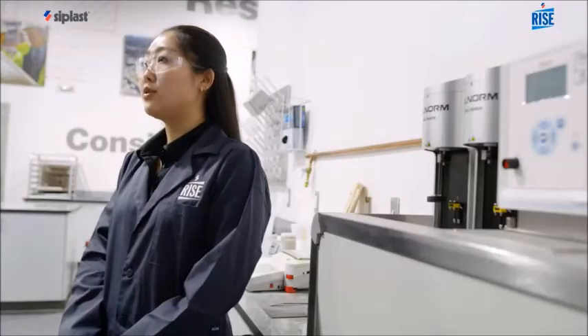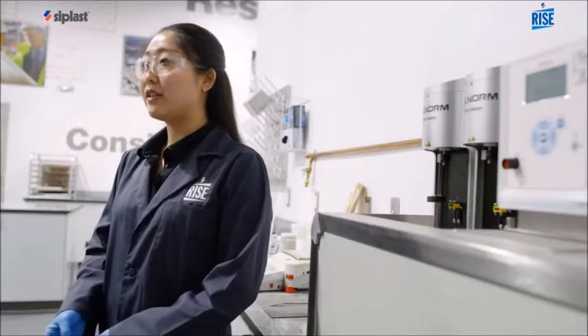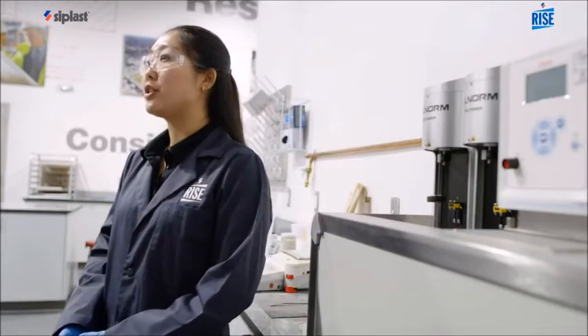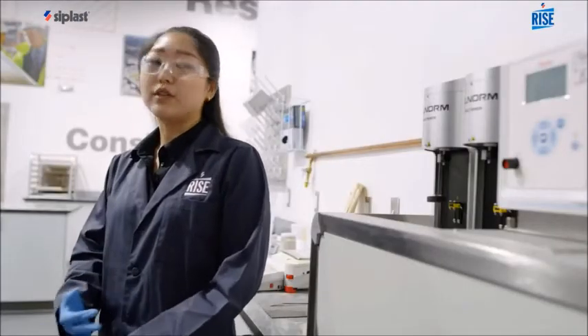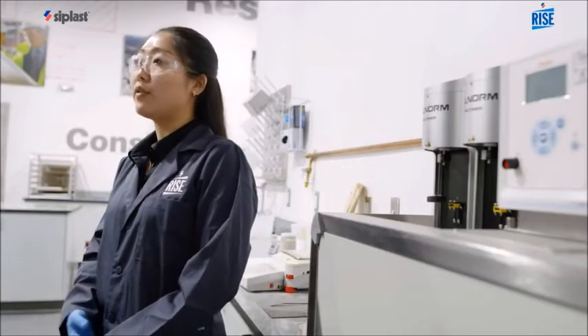We always test QC at the end of the batch. So once they're done formulating, we would check once. And if everything falls within the spec, that's good to go, and we would package it. If it falls just a little bit outside of the range, we can always make a correction to our formulation. So we would either add the accelerator or the inhibitor, depending on if the gel time is running short or long, and let the production line know, and we would make the correct adjustments. And after that, we would run the QC again to make sure they fall within the spec.